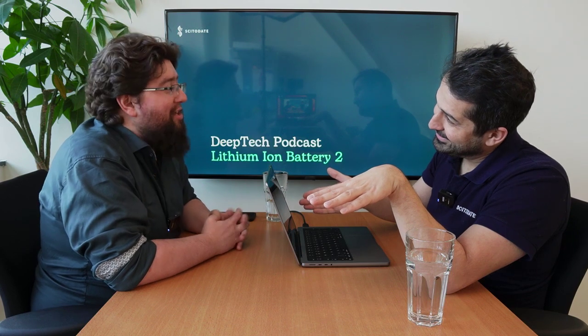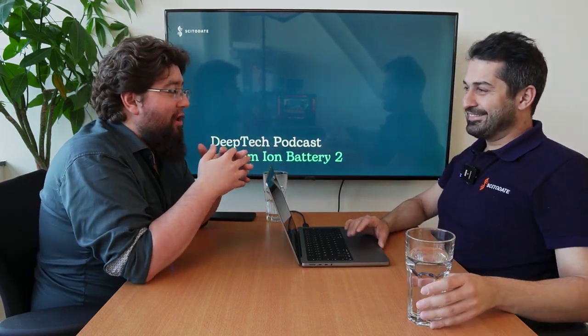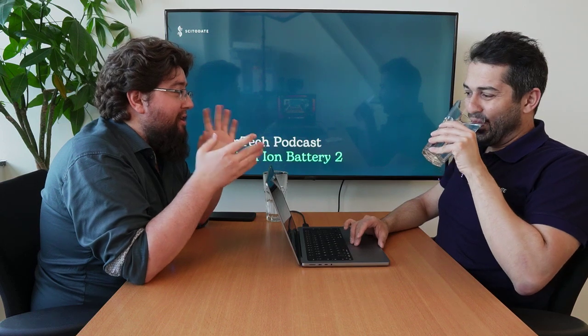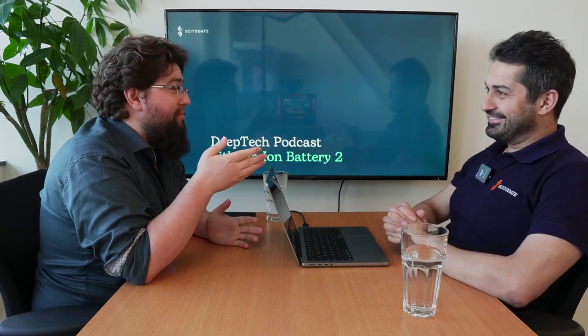It's so interesting that all of these totally different factors cause the same effect. So lithium plating is why batteries get less efficient, but it can happen because it's too cold, so the layers are too tight. It can happen because you charge it too fast and they stay on the surface, or it can happen because all the parking spots are full, so they stay on the surface. So again, here you see why a lot of things are important: how to control and study this.